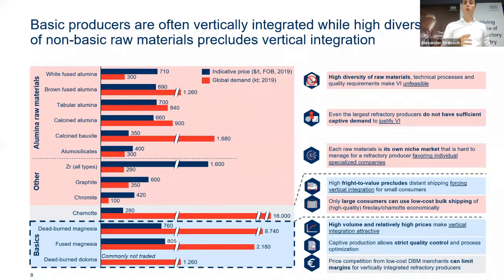So when we look at the alumina raw materials, only the global demand, then we see that the demand is around 1 million tons. So between, let's say, 300,000 and 1.3 million tons. So this is the order of magnitude. For the specialty raw materials, it's even smaller. So we have about 300,000 or 100,000 tons. And obviously you would not start a chromite mine if the global demand for chromite for refractory is 100,000 tons, right? This is just a byproduct in reality.